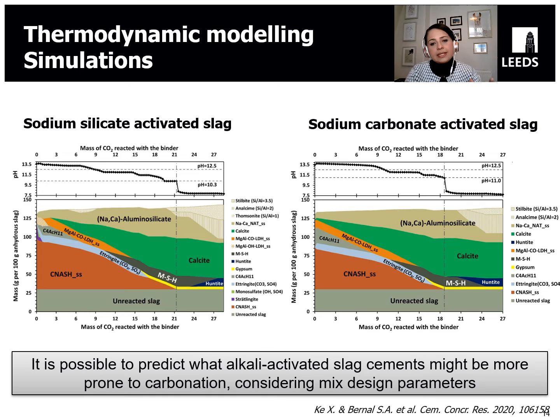But what is important is that this thermodynamic modeling approach enables us to predict which type of slags with certain composition are more prone to carbonate more than others when they are activated with certain activators. So it enabled a quick scanning of what will be the best, or potentially the best, activation conditions to produce a material that will be resilient to carbonation.